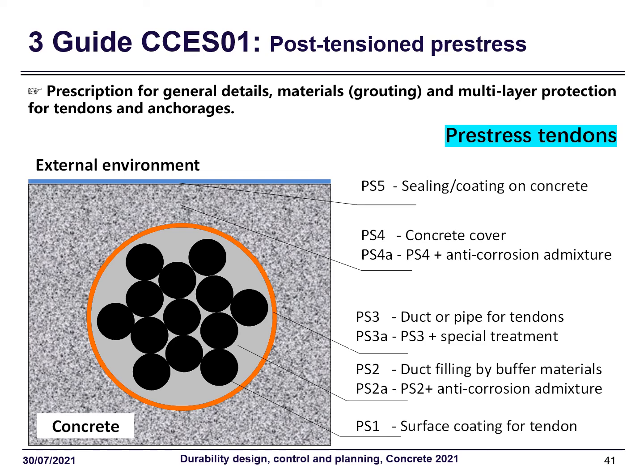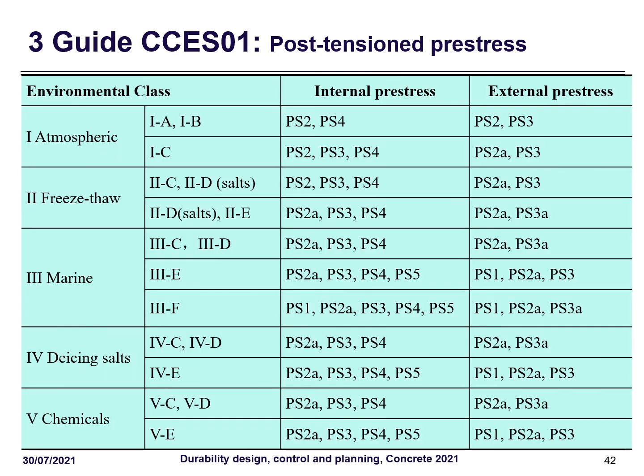And in the last part, we prescribed the durability requirement on the post-tensioned prestressed concrete. Post-tensioned prestressed concrete is special because the corrosion of this steel or strand will directly endanger the safety of the structure. So in this chapter, we apply mainly the multi-layer protection for tendon and anchorage. Here we can see that, for example, for tendons, from inside to outside, we have respectively the protection measures as the coating for tendon, duct filling, duct or pipe, the concrete cover, and the sealing coating on the external concrete surface. And on this table, we just attribute this combination to the different environmental classes and intensities. Generally, for the most severe exposure, you need all. For some very slight action, you need only 1 or 2 measures to counter.